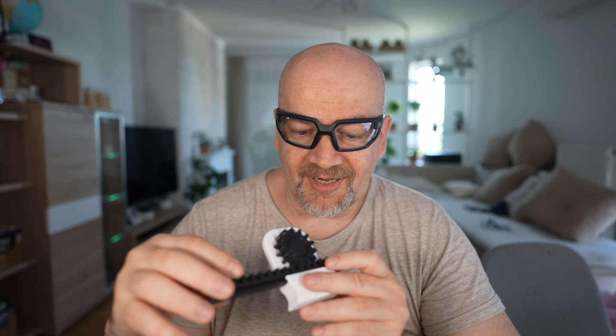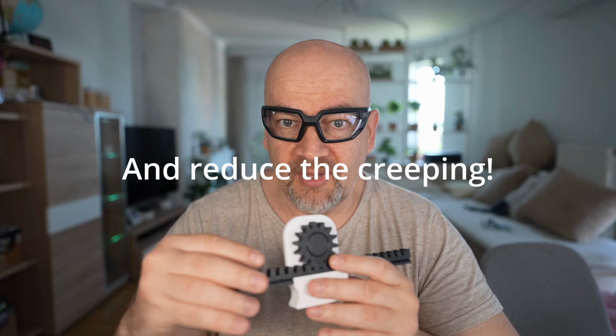I have the feeling that I'm still missing some kind of test where all these graphene filaments will start to shine. Maybe some bigger load, longer test, bigger speeds or something like that. Because yes, here for example I can measure some improvement, but I wouldn't say that it is significant improvement compared to the regular, I don't know, PETG or PLA. About its mechanical properties, yes, this graphene-reinforced improved the stiffness and rigidity of the filament, but on the other side, especially with the PETG, the layer adhesion is very weak. Yes, we can improve this by printing on much higher temperatures, for example on 270 to 280 degrees Celsius, we can go this high with the PETG if the printability is okay.